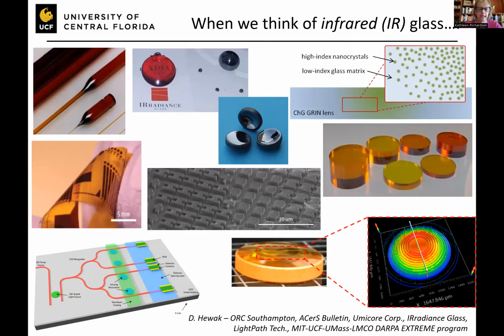If we think about infrared glass, there are things that we can do very similar to what we do with oxide glasses, but what's special about them is they transmit in the infrared. And that means most of them, depending on their composition, don't transmit in the visible. In the upper left-hand corner, you'll see some arsenic sulfide glasses or sulfide glasses that do have some transmission in the visible. But to large part, unless they're doped very specifically, which typically means in chalcogenide glass speak, without selenium, these glasses typically are black or silvery in color, such as shown in the middle.